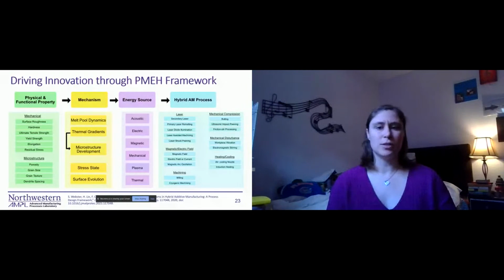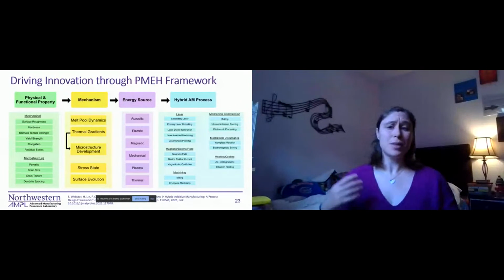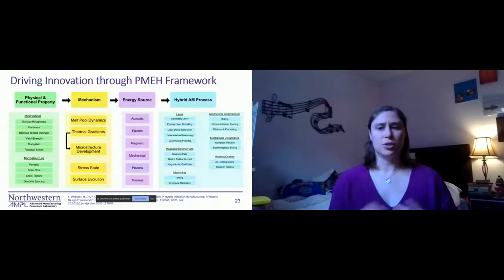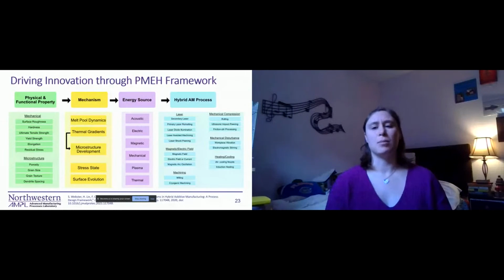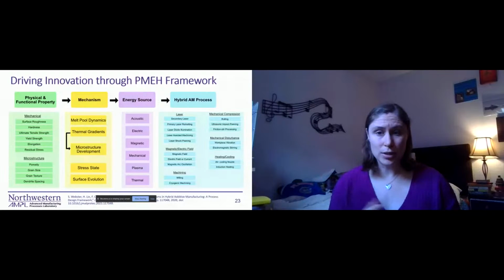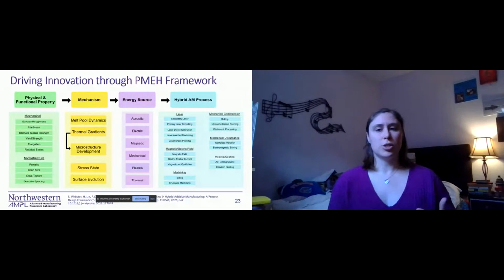Machining is pretty obvious, between milling or other types of machining to reduce surface roughness. Mechanical compression, which includes rolling, ultrasonic impact peening, or friction stir processing. Mechanical disturbance, which was the acoustic energy that I was talking about before with workpiece vibration. And finally, heating and cooling, where cooling nozzles or induction heating were used to influence the material.